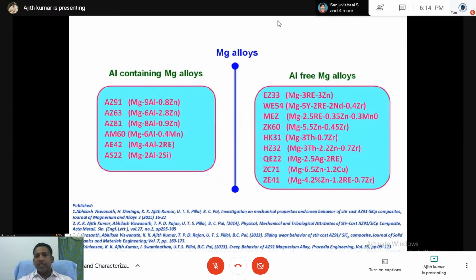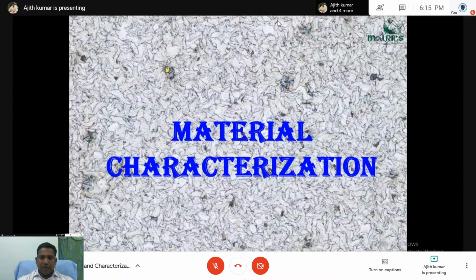We can classify magnesium alloys into two categories: aluminum-containing magnesium alloys and aluminum-free magnesium alloys. With respect to composition, we put coding on magnesium alloys, for example AZ91. AZ91 means 9% aluminum and 1% zinc in magnesium. Every coding is like that. AE42 means 4% aluminum and 2% rare earth. That is AE42.